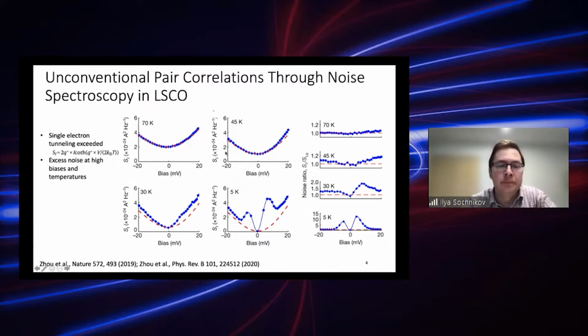But as you go to lower temperatures, you start seeing excess noise in the data as compared to the expectation from a simple resistor model. That noise gets higher at low temperatures, but the surprising part is that it is present at temperatures even higher than the bulk critical temperature of the leads themselves, right? The leads' critical temperature was measured separately. So you can see this difference between the expected and the measured amount of noise, and there's clearly a lot more going on in the data compared to the expectation.